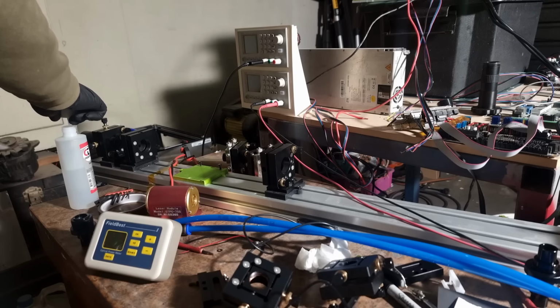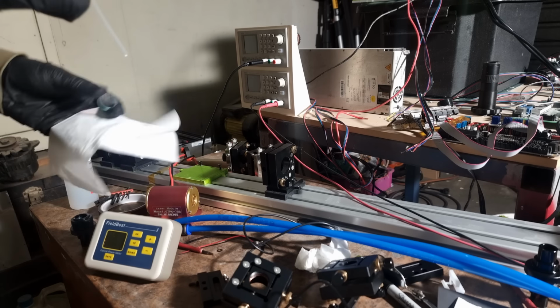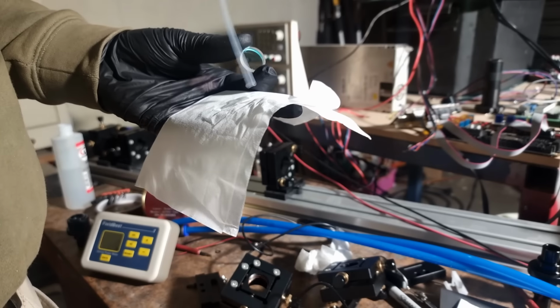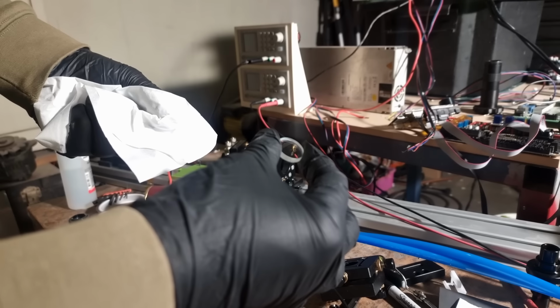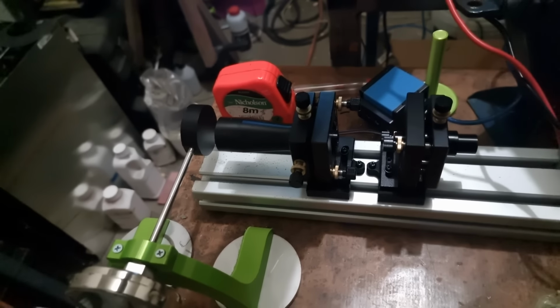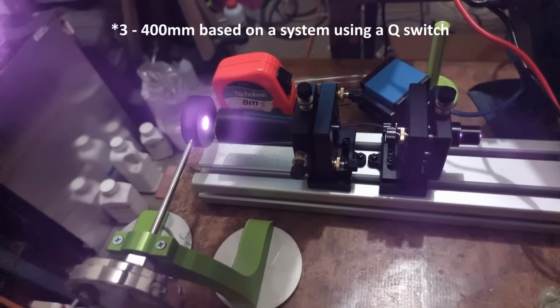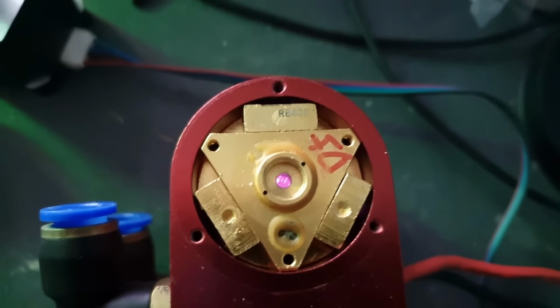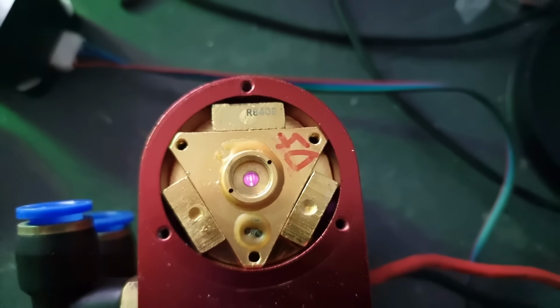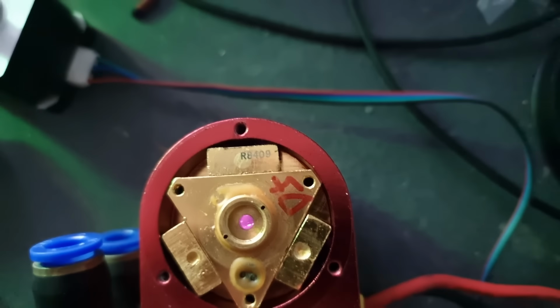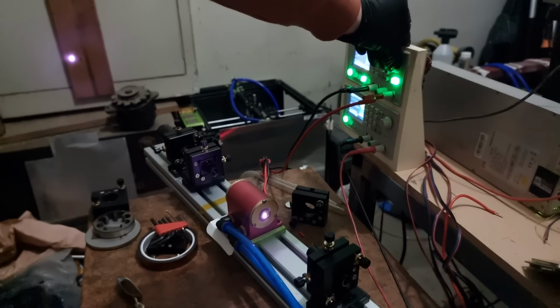Even now I can only speculate based on what I have read, but suspect that the flat plane mirror is an 80-20 split, and the HR mirror has a radius of curvature somewhere between 1 to 2 meters. Gleaning information from sellers, it seems like 400mm is the typical cavity length, and switching over to new mirrors would bring the power up to just shy of 40 watts. The particular pump I'm using is a GTPC-75S, which as you may have guessed is rated at 75 watts, but this is rated at a rather awkward 29 amps whereas I could only provide 24, the max an RD series buck converter can supply.